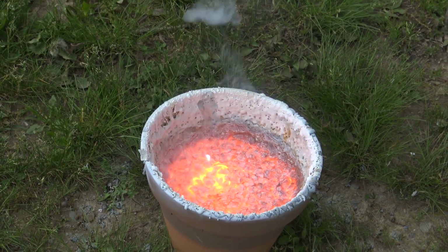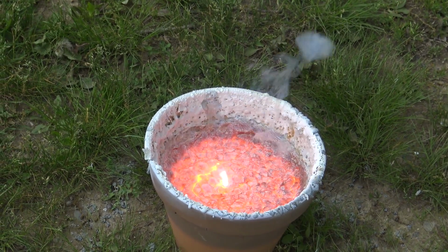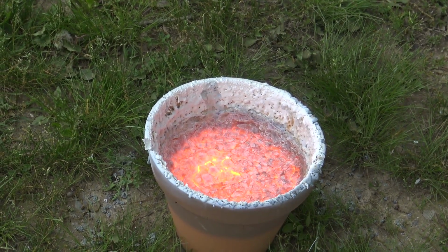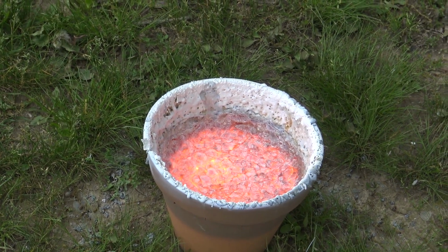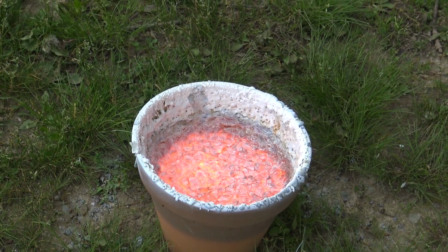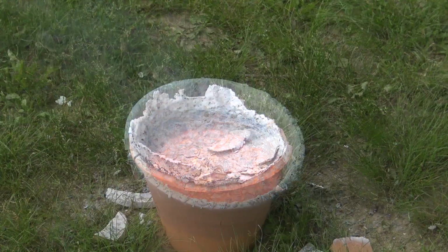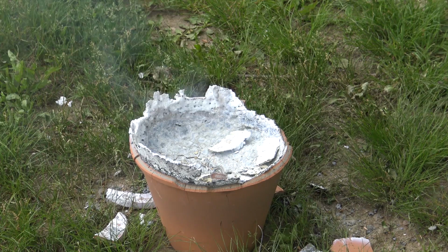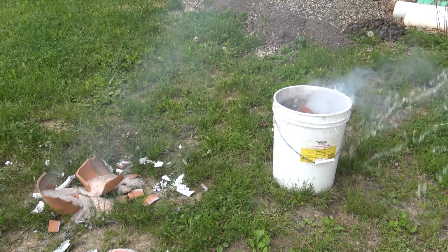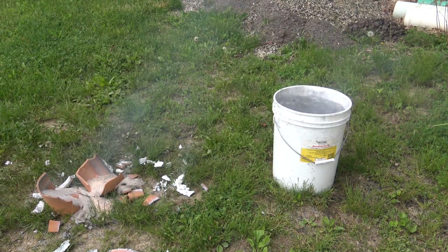Once the ethereal blue flame dies down and cools slightly, we'll have a mixture of silicon metal, aluminum oxide, and aluminum sulfide, which will react with moisture to make deadly hydrogen sulfide and less deadly aluminum oxide. You may have figured out the use for the bucket of water already, but for those that haven't, now we just stay far away and wait.